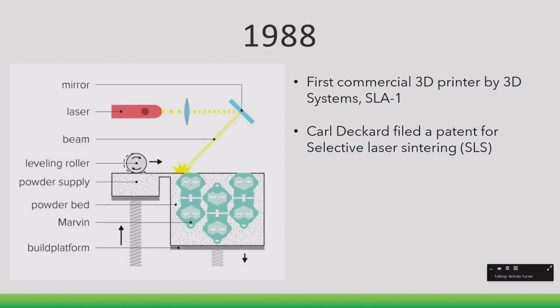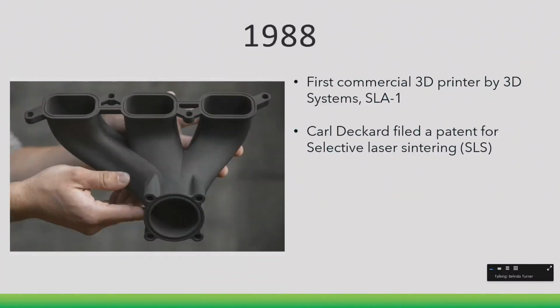So this works slightly differently. It has a tank of basically powdered plastic, which will get laid on in very thin layers by a roller, and then that gets hardened and sintered together via laser, generally from above, and then the tank will slowly lower with the parts cured inside a cake of powder, as it's generally called. So the parts out of this generally have a rougher surface texture, but the main benefit of this is you generally don't need any sort of supports because the powder itself is supporting the part as it goes along. So you can get away with some very complex parts which don't need very much cleanup afterwards, other than removing any residual powder which is on the surface.